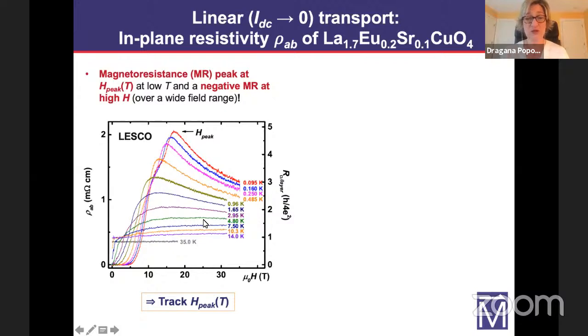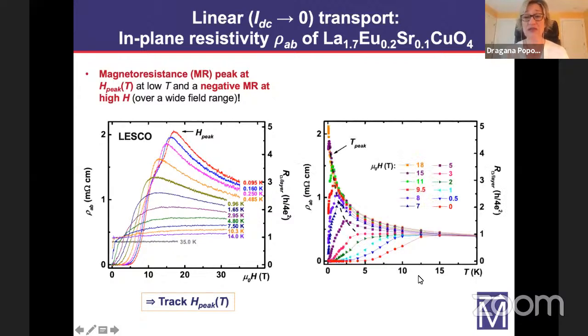And from this, you can also extract the temperature dependence of the resistivity for different magnetic fields. And here we are showing all the results up to 18 Tesla for clarity. So from here, obviously, you can determine TC. You see that as you increase the field, TC is suppressed, as you would expect.